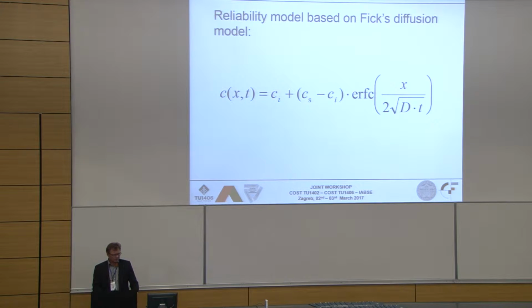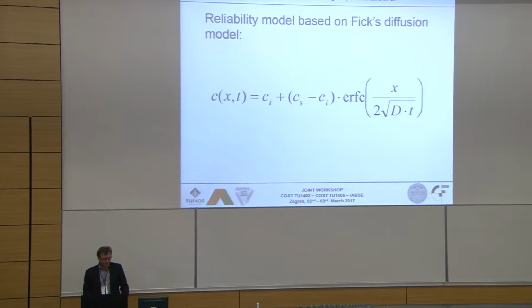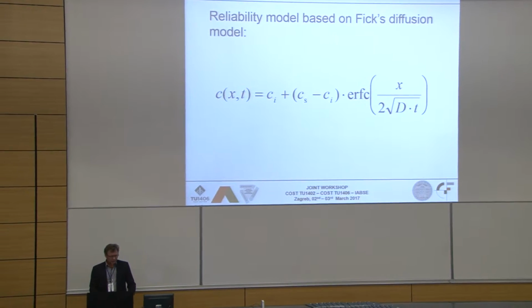So this is the reliability model. We have the concentration at the armor as a function of time. So if you put x equal to the distance from the surface, we get the location of the steel armor. We have the initial concentration. We have the difference between the surface concentration and the initial one, which is a driving factor. You have the error function, and you have the distance again to the armor, and then you have the diffusion coefficient and time and the square root of that. So this is how the concentration is changing with time, and when this reaches the critical level, then you have failure. So it means it's initiation of corrosion. It is not like ultimate capacity or failure of the armor. It is the starting of corrosion at the armor, which is the criterion here.